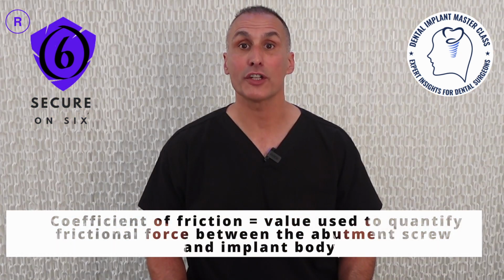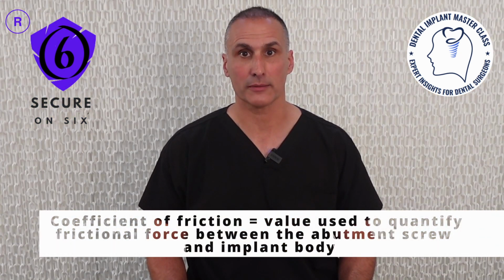The relationship between applied force and screw preload depends on various factors, including shank thread hardness and shank surface finish, all of which affect the coefficient of friction of the screw shanks. No machine surface is entirely smooth, and after the initial torque and unscrew process, there is a flattening out phenomenon of the high spots on the machine surfaces, resulting in more even contact at the flanks to implant thread contacting